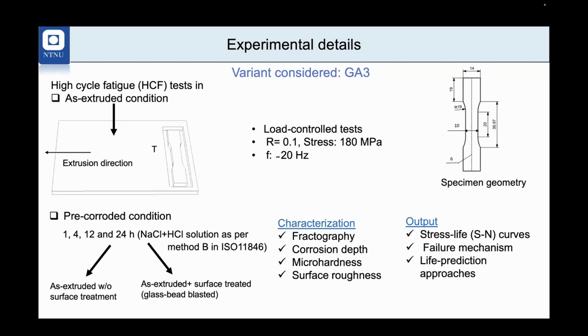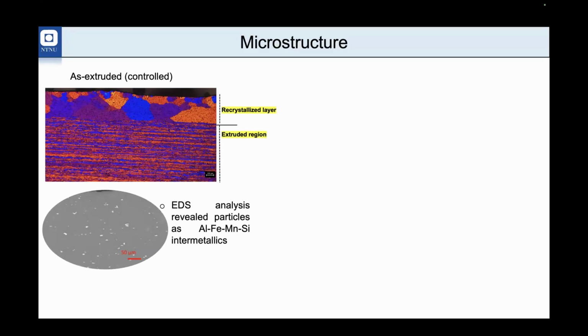We did a thorough microstructural characterization in terms of corrosion depth, micro hardness, post-fracture fractography, and surface roughness. These are the outputs that we received: the stress life curve, failure mechanism, and life prediction approaches. Before I go into the details, I want to show you some of the microstructure. This is the as-extruded microstructure. As you can see, at the surface we have a recrystallized layer with very big grains along with some small grains. The recrystallized layer is followed by the extruded region, which has a very fibrous microstructure consisting of elongated grains. We also have particles, which are iron-rich intermetallics, on which we did EDS analysis, which revealed the particles as shown.